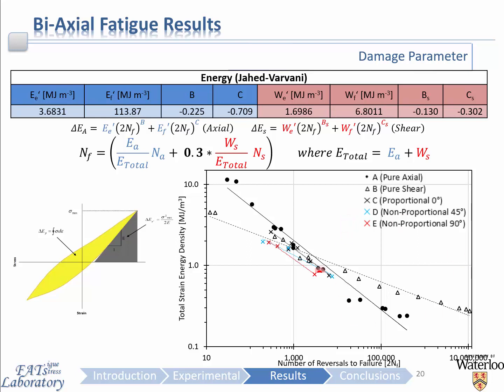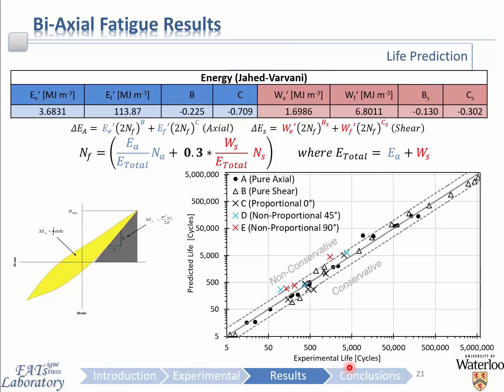You can see in the image on the right here the total strain energy density versus number of cycles for all of the 5 loading paths that were observed here. Now looking at the fatigue life prediction for all of the 5 loading paths, it can be observed that virtually all of the fatigue life predictions are within a band of plus or minus 2, which can be considered to be a very good and reliable prediction. The non-proportional cases are trending towards non-conservative, which is a focus of future work in refining this damage model.